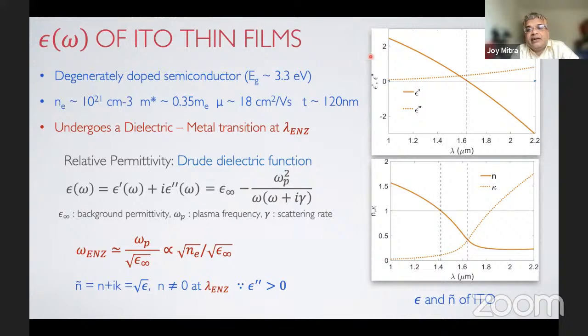And you can see here that in the visible, the epsilon is a positive number, whereas above lambda ENZ, it becomes negative. Therefore, it undergoes a dielectric to metal transition, a driven dielectric to metal transition, at a particular wavelength which we call lambda ENZ. And the value of lambda ENZ, or the ENZ frequency, can very easily be tuned. If you look at the Drude model of relative permittivity, it depends on the number density of the electrons in the system and the background permittivity epsilon infinity. And epsilon infinity is more or less a constant. Therefore, by changing the electron density of the system, we can very easily tune it.